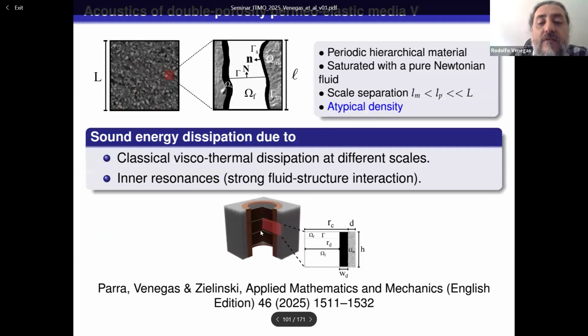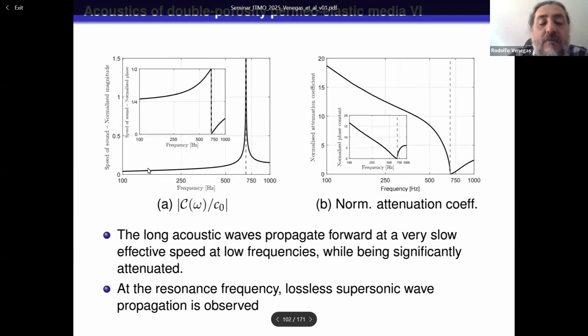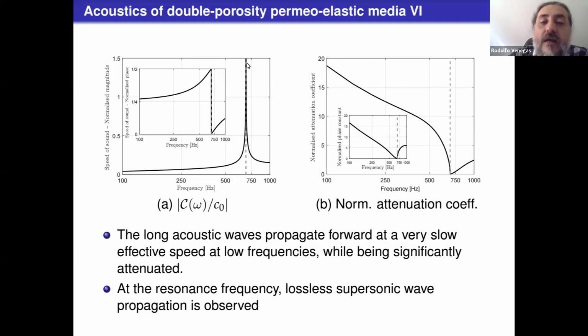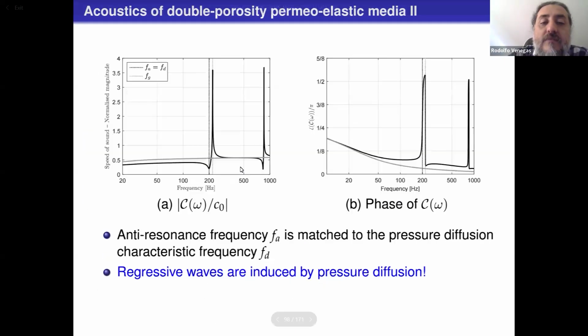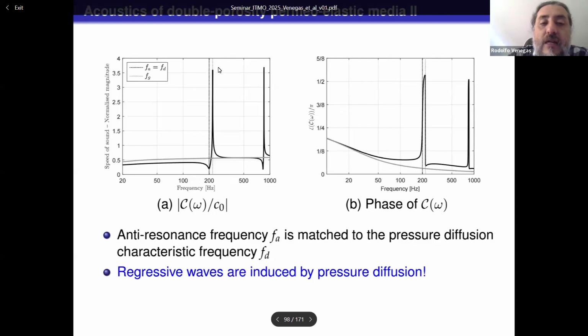Now imagine we have, let's say, a perforated panel where we place a tube in it, and within the tube there are some plates that disconnect this fluid phase. In this case, we have an atypical density, and the speed of sound behaves in a rather particular manner. It starts increasing and it goes like this. It becomes supersonic at the resonance frequency of the plate. There's no anti-resonance frequency here, as we've seen in the previous case. So it goes directly to a maximum, but without having a minimum.